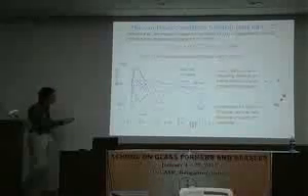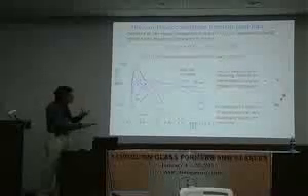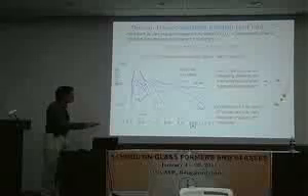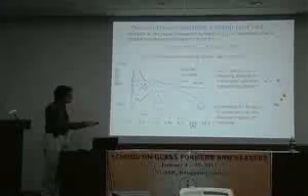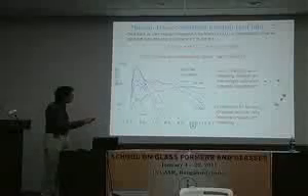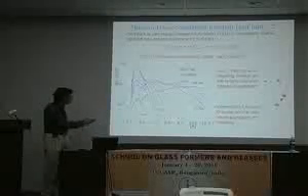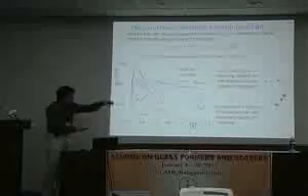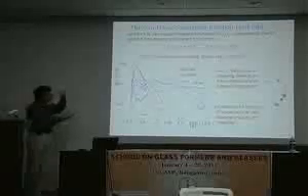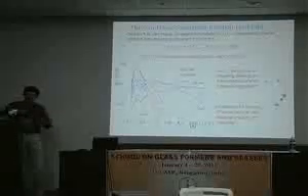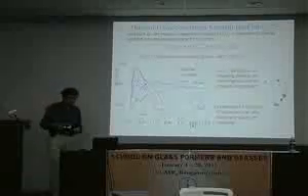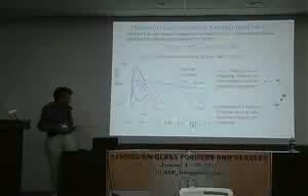These bumps correspond to nothing else than if you would trace a tagged particle, it's rattling around. This is the first hump here, and then it's jumping to a new position. This is this hump here, rattling around again, hop. And so these successive humps that get smeared out at larger distances are nothing else than this rattling and hopping dynamics of the sodium atoms. Okay, so you see that by looking at this quantity, you start to understand already quite a bit about the transport mechanism in the system.